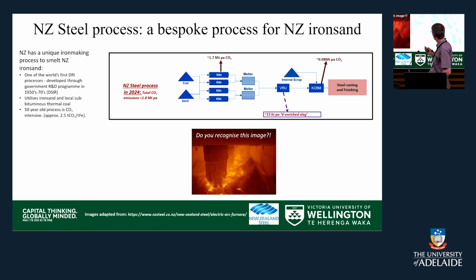Then those melters go through a unit called a vanadium recovery unit. And that's kind of important for us. We've got about 0.5% of vanadium pentoxide in the original titanomagnetite. And that vanadium recovery unit takes off a vanadium-enriched slag, which is about 1 to 1.5% of the world's primary vanadium supply from this little tiny steel plant.